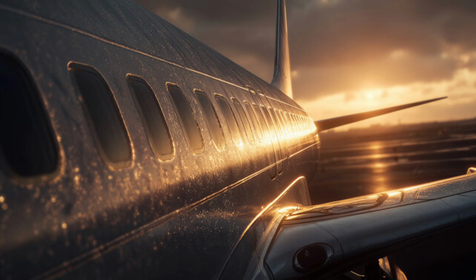Once a crack reaches a critical length, the remaining intact material can no longer redistribute the load. The structure transitions from stable to unstable in an instant. What has taken thousands of flights to develop can reach catastrophic failure in less than a second. When that moment arrives, the physics is unforgiving. Cabin pressure seeks equilibrium with the outside environment.